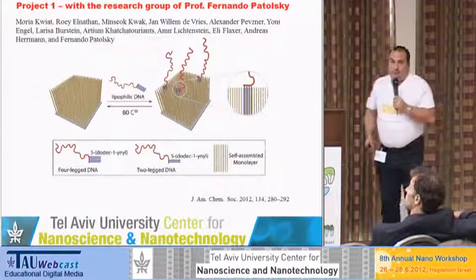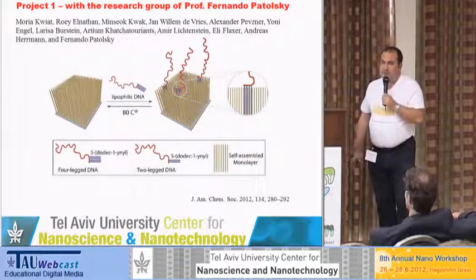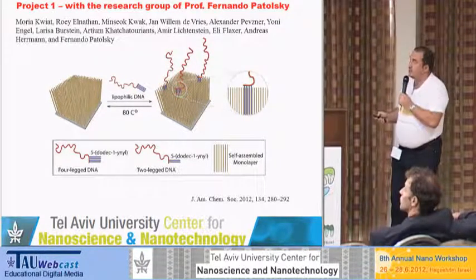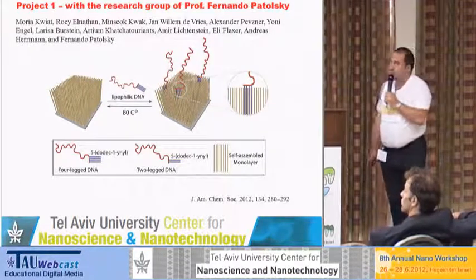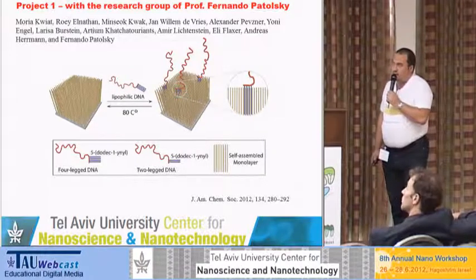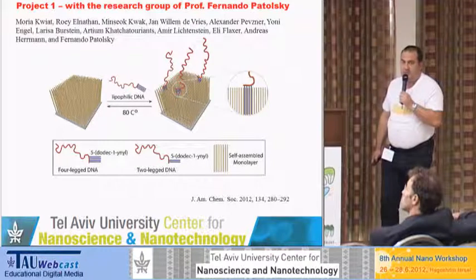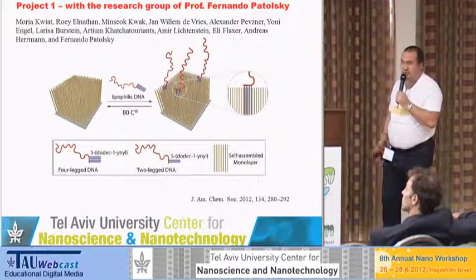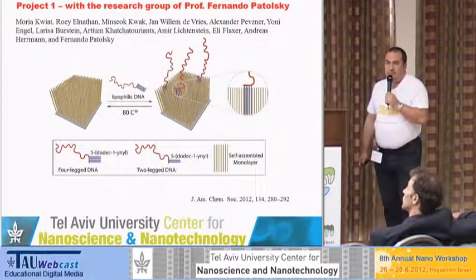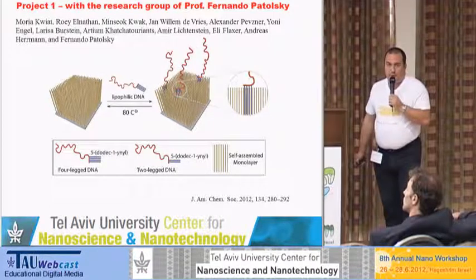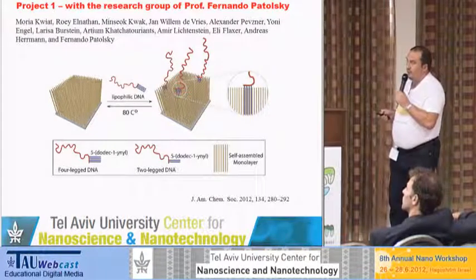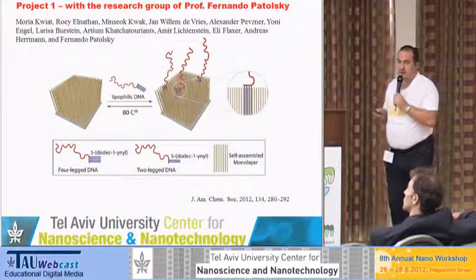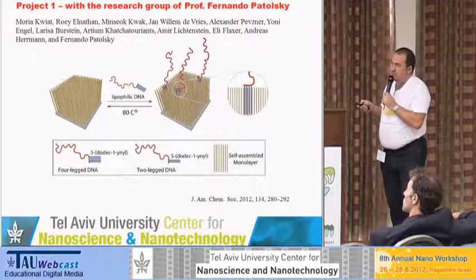Now we are going to the projects which I mentioned. One of the projects is in collaboration with the research group of Fernando Patolsky. They build self-assembled monolayers of lipophilic DNAs on the silicon oxide and the gold surfaces. Such self-assembling monolayers are of great interest because of their remarkable properties in terms of electrical properties, chemical properties, optical properties, and then they further functionalize the surface by attaching so-called amphiphilic DNAs, which have hydrophobic tails, and they are just anchored in the self-assembled monolayer of the lipid DNA.